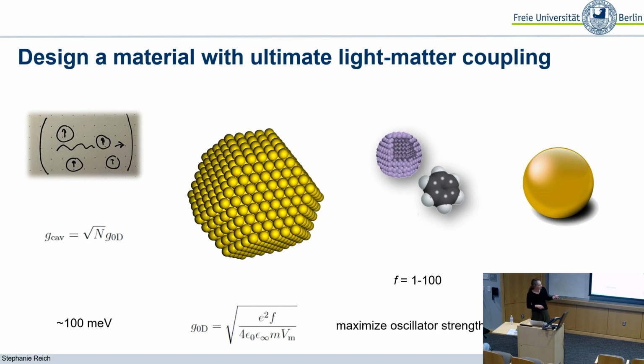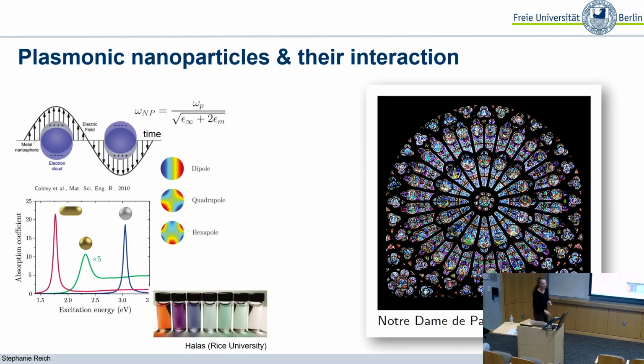If you look at oscillator strengths of things like organic molecules, such as the benzene molecule shown here, or a quantum dot, a cadmium selenide quantum dot, you will typically find that they're on the order of 1 to 100, because that's the number of electrons that you can excite. We decided to go to gold nanoparticles instead, because their oscillator strength is many orders of magnitude larger. And I want to give you a brief introduction into gold nanoparticles and their plasmonic properties. I heard some of you talking about listening so often to plasmonic talks, but you need to get the introduction again.